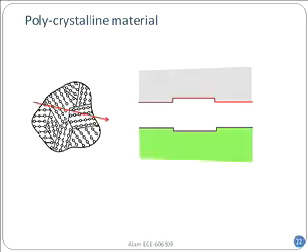No sharp band gap. And therefore there is no notion of one single band gap anymore in this particular case. Every time the electron goes through a grain boundary, it will get scattered because the band gap has changed. As a result, the transport will be a little bit more difficult. But the notion of a band gap still exists, the density of states still exists. It is just that the band edge is a little bit more amorphous, I mean, not clearly defined anymore, depending on which direction you are coming from.